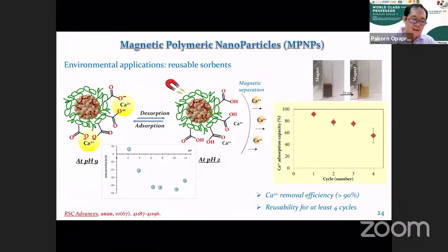With similar materials, because they have carboxylate groups, they can complex with various types of metal, especially metal ions that have two positive charges, for example, calcium. If we use this material as an adsorbent to adsorb calcium, it shows very good adsorption capacity. And the major advantage over normal adsorbents is that after adsorbing all the calcium, we can collect them back by using an external magnetic field.